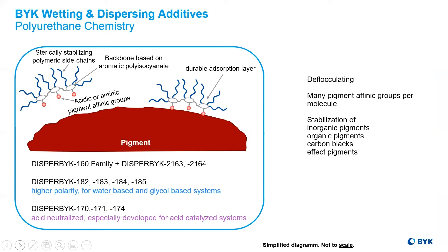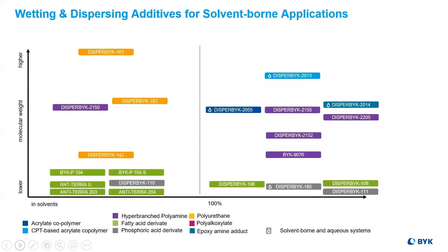Not only did we meet those functional needs, but we also offered a wide range of products to meet the needs of the plethora of systems for new organic pigments in this emerging market. Deflocculation additives were providing a function of reducing grind viscosities, obtaining the primary particle size to enhance color effects, and assured flexibility in different end uses. In producing polyurethane additives, we understood the dynamics of molecular weight, the nuances of the chemistry and the chemical backbones of the additives, and the functionality of the pigment affinity groups to provide a diverse range of products.